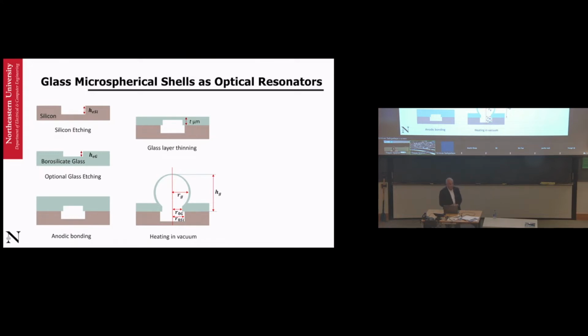We take borosilicate glass. If any of you have a chance, you can go to the Corning Museum and blow glass there too, not too far away from here. And it's literally that, just that we do this on a chip. We use what is called an anodic bonding process, by which we bond glass to silicon with no other material but molecular bonds between glass and silicon. Once you do that, you have a cavity that is pressurized, in this case say 1,000 torr, a little over atmosphere.